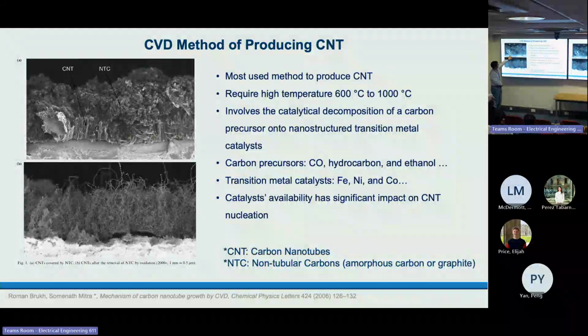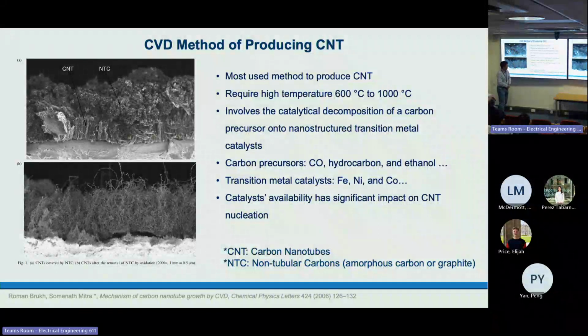We can see obviously, this is the catalyst layer, and this is the carbon nanotubes layer. Onto the carbon nanotubes is the NTC, we call it non-tubular carbons, which contains amorphous carbon or graphite. Because the carbon nanotubes layer forms here, the carbon precursor is getting harder to reach the nanostructured catalyst. That's the reason why the NTC layer is formed onto the carbon nanotubes layer.